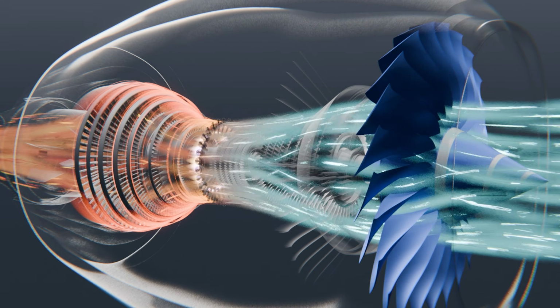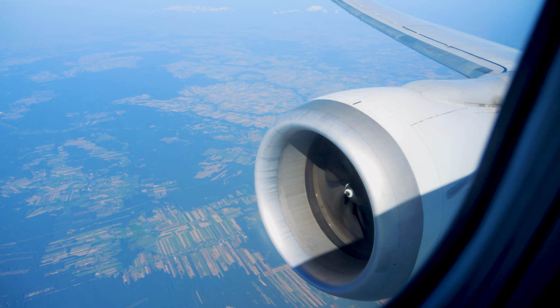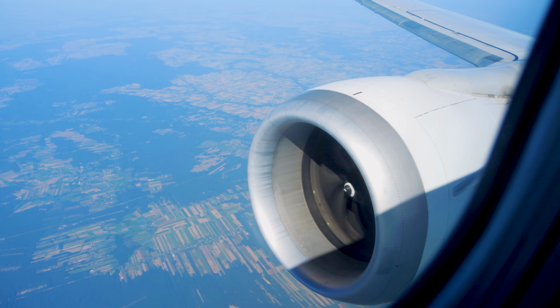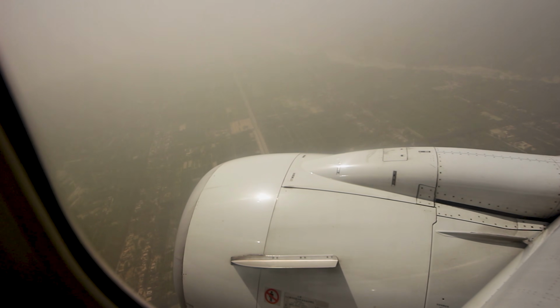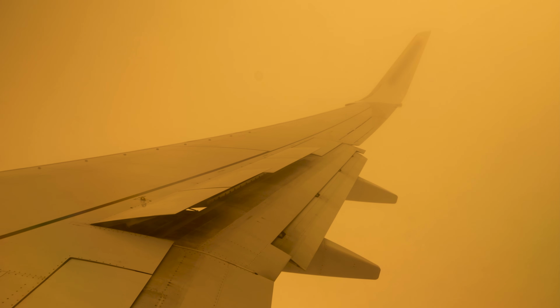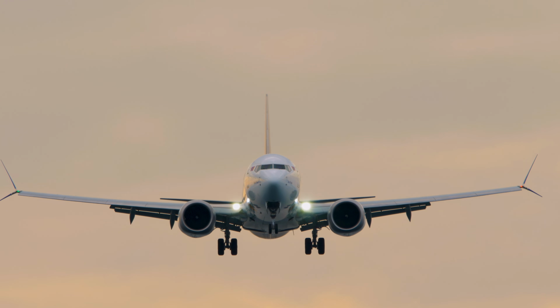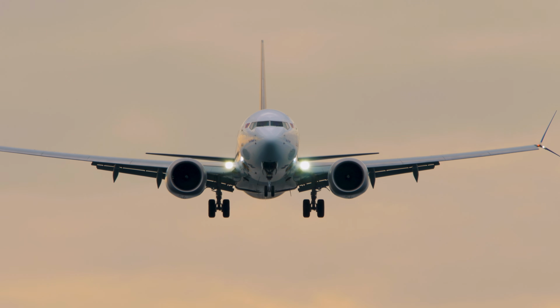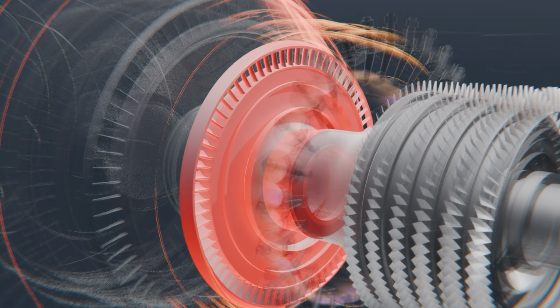all while they're glowing hot. To make matters worse, at these temperatures, oxygen wants to react with the metal of the blades itself. And on top of all that, the air rushing through the engine often carries dust, sand, and pollutants that can damage and erode the surfaces inside. And somehow, these blades have to survive this punishment for tens of thousands of flight hours without deforming, cracking, or failing. They really determine how efficient you can make the engine, because you can't make the engine so hot that the blades can't withstand that temperature. So they determine the maximum temperature of the combustion chamber and therefore the maximum efficiency you can realize with a jet engine.